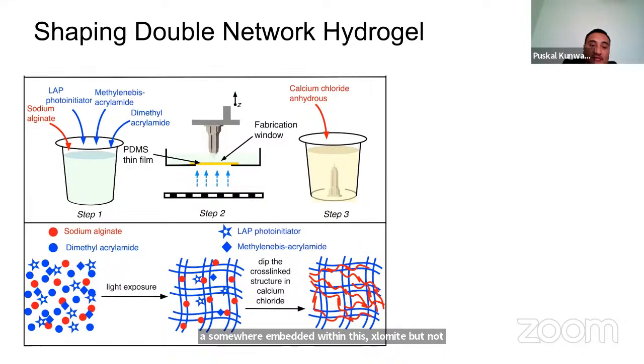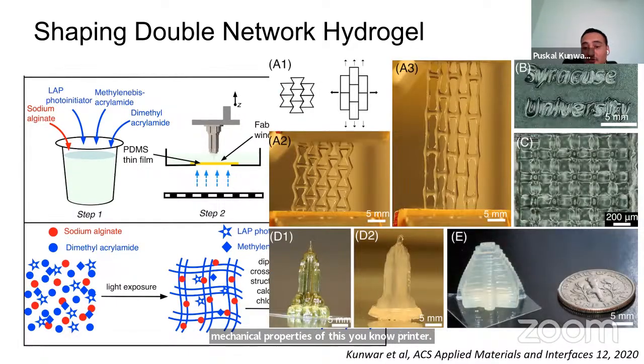Then later we dip this whole structure into a calcium chloride solution. Now the calcium starts to diffuse inside, and as it goes inside, it starts to form another network. This way we can enhance the mechanical properties of this printed structure. Here are a few of the printed structures with a resolution of 200 micrometers.